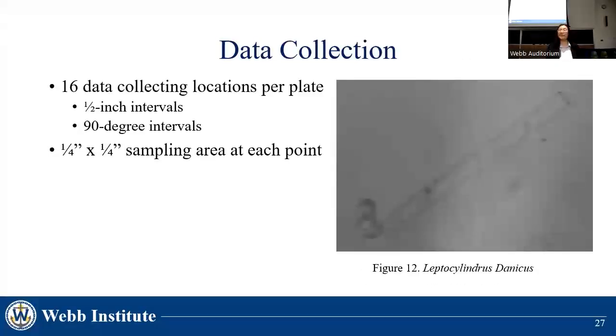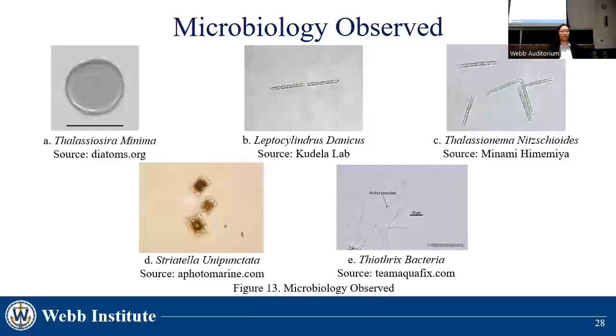Figure 12 shows a still image of the Leptocylindrus danicus, a common diatom of the Long Island Sound, which was observed 1/2 inch away from a UVC LED on an epoxy-coated plate. In the examination of all test plates, 5 separate organisms were able to be identified, including several diatoms. For display purposes, we have chosen to use professional microscopic images, seen in Figures 13A through E.